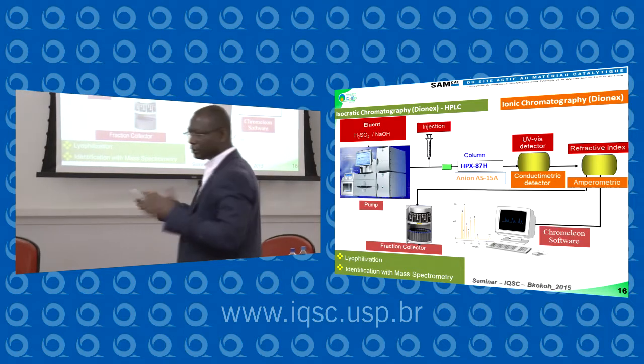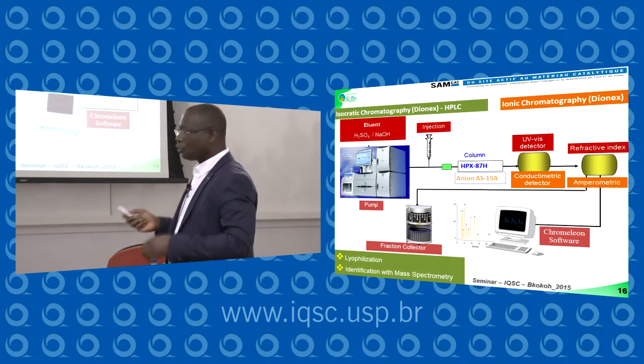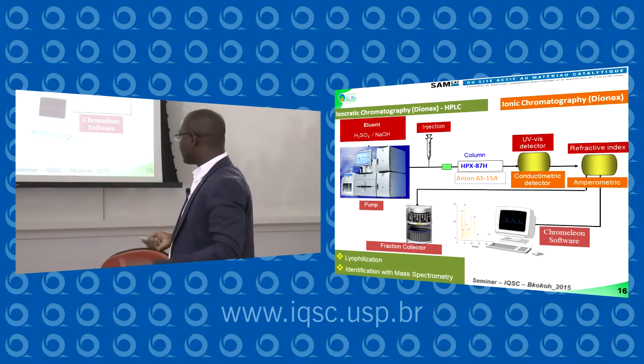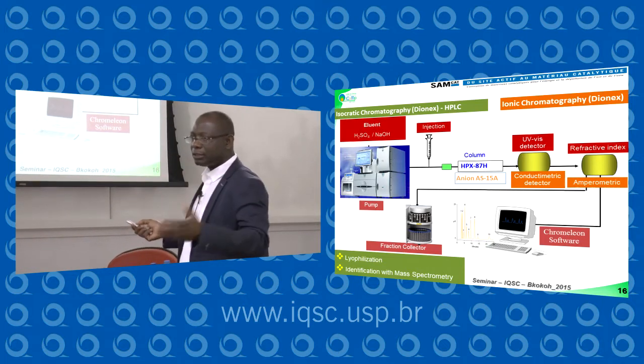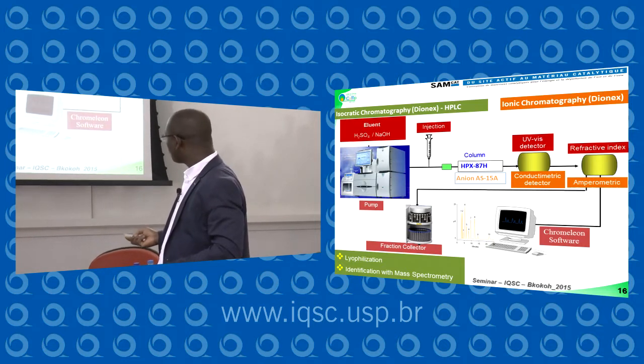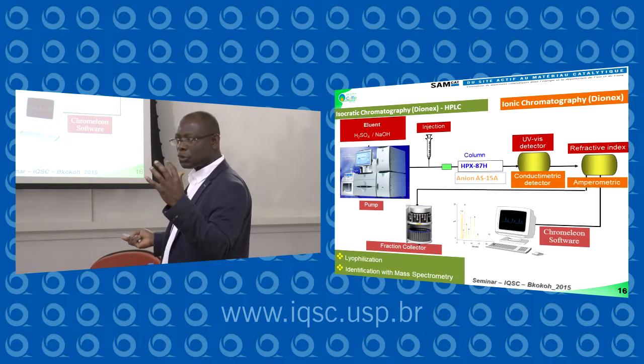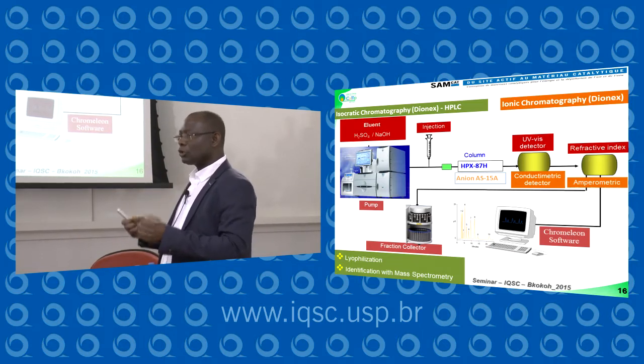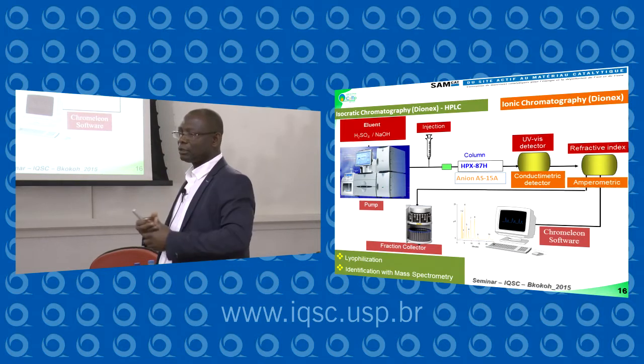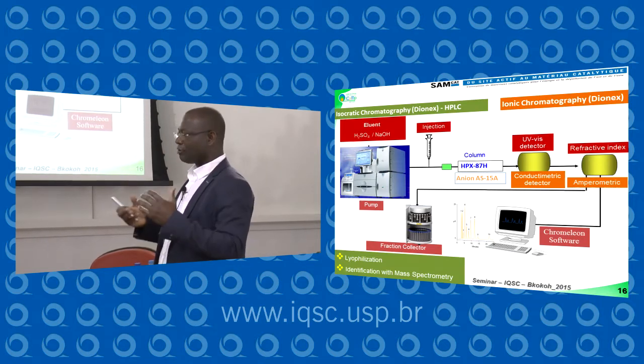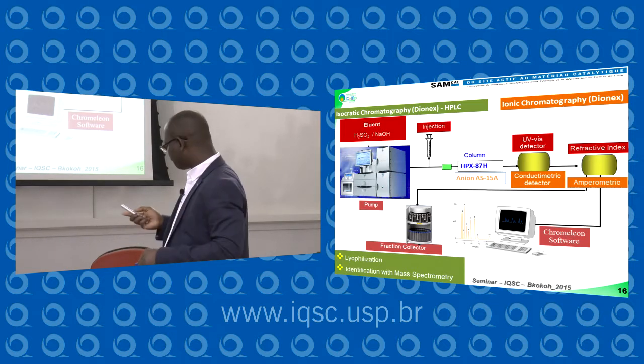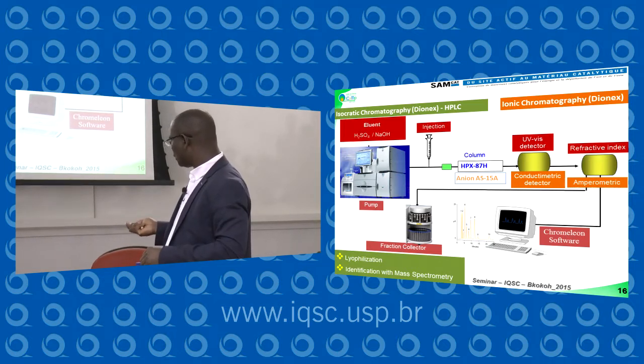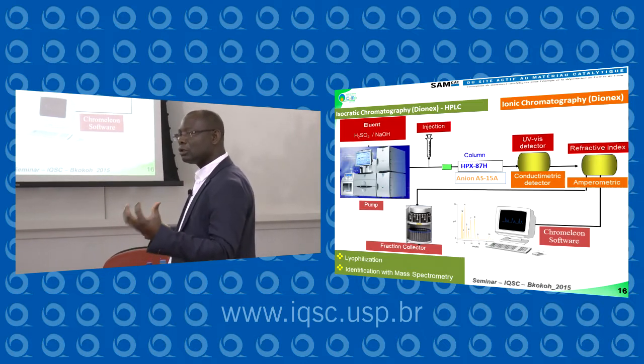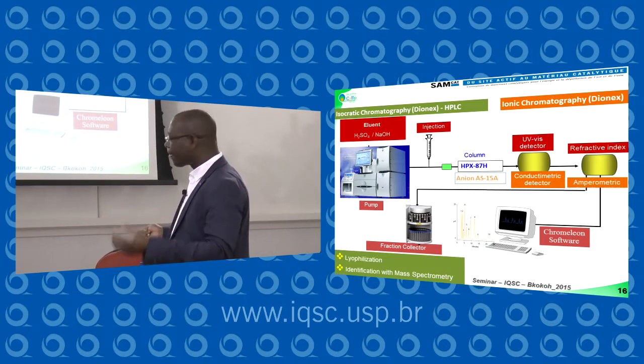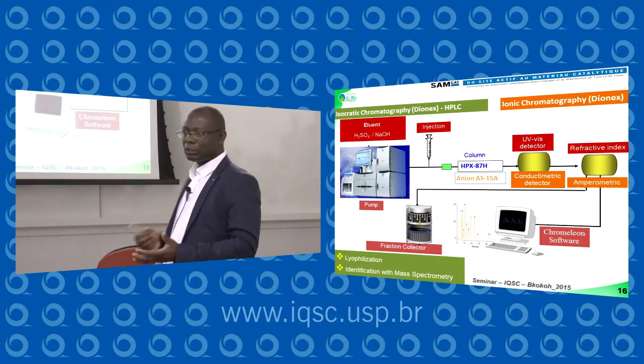And after, you can collect all the fractions you have. And after, this is chemistry. You remove the electrolytes by a resin, Amberlite, DOWEX, and so on. And after, you can lyophilize, because glucose is very fragile. You cannot use an evaporation system, for example. An evaporator is not good because it's very strong in pressure. So you lyophilize your solution without electrolyte, and after you can do, if you want, mass spectroscopy.